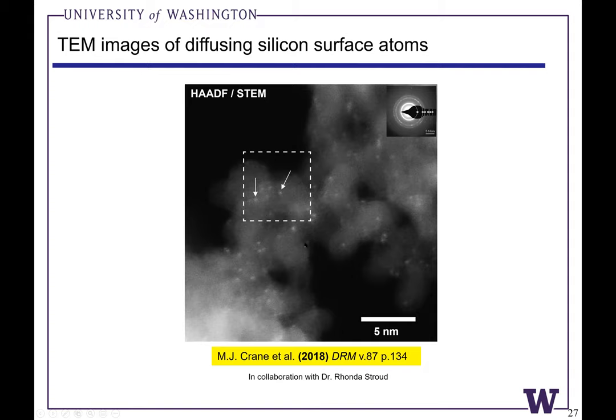So we started to do some electron microscopy of our starting materials and recovered materials, our control samples that supposedly had no silicon. We were collaborating with Rhonda Stroud at the Naval Research Lab in Washington, D.C. And Rhonda has an amazing scanning transmission electron microscope from the NION company, where Rhonda can zoom in and effectively collect X-ray fluorescence spectra from individual atoms in a variety of nanoscale materials. So we sent our starting materials to Rhonda and said, we want to know what's in this material at a microstructural level. There shouldn't be any silicon there. And Rhonda did some quick measurements with her group and sent us some images back and said, I've got bad news. You actually have silicon on the material that you said should be silicon free.